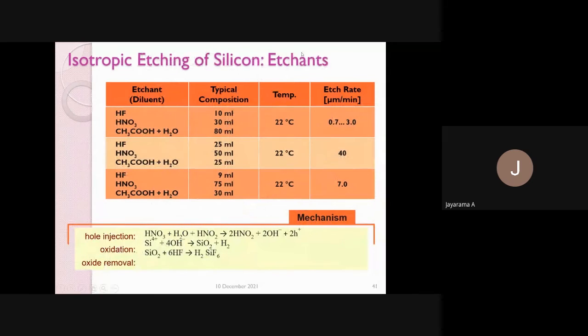Isotropic etching of silicon etchants - this is a table which gives information about different etchants. This is the combination of HNA, meaning hydrofluoric acid, HNO3, and acetic acid. Here typical composition they have taken, so the etch rate is 0.7 to 3 micrometer per minute.